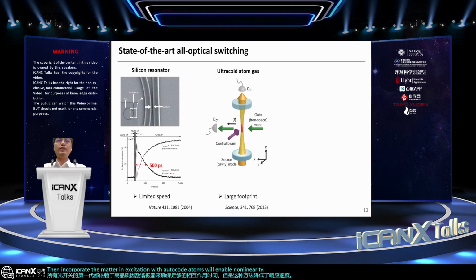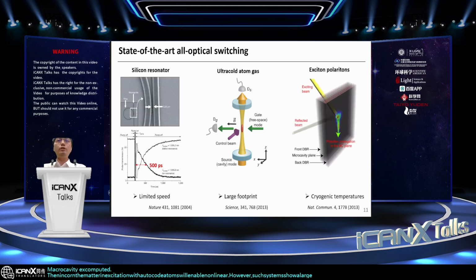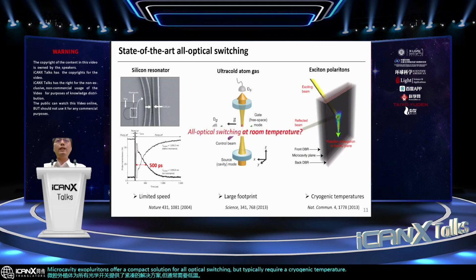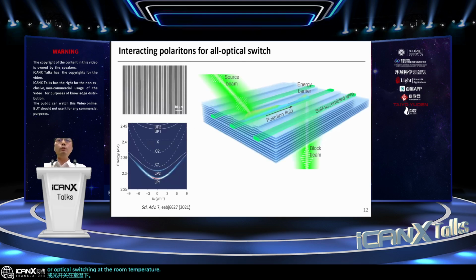However, such systems show a large footprint. Microcavity exciton polaritons offer a compact solution for all-optical switching, but typically require cryogenic temperatures. Therefore, we ask a question: can we achieve all-optical switching at room temperature? We address this challenge by creating a self-assembled perovskite microwire integrated into a cavity. These microwires sustain stable exciton polaritons at room temperature.